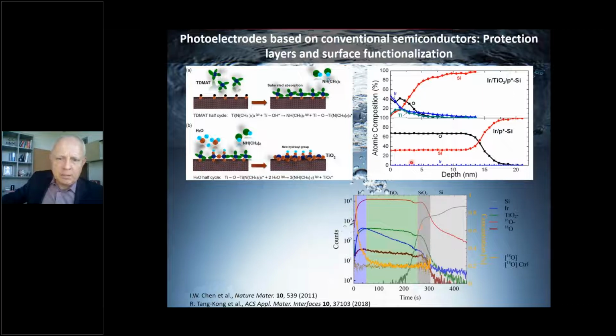We've studied in a relatively small number of cases the mechanisms for the improved stability associated with TiO2 and the mechanisms for failure of these coatings in the cases where they do fail. And we find that actually the principal mechanism of failure is not oxidative attack of the underlying silicon. This is an experiment using isotopic tracers to characterize oxygen penetration into the structure. We don't find any evidence of oxygen tracer penetrating into the underlying layers and oxidizing the silicon during these experiments.